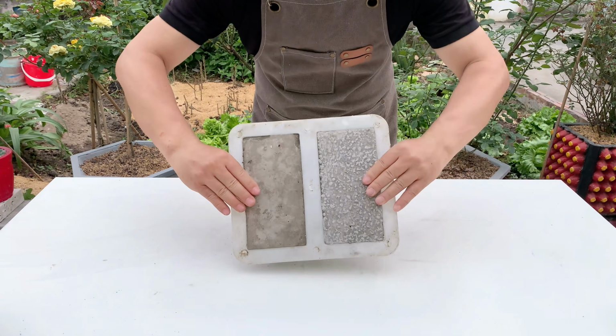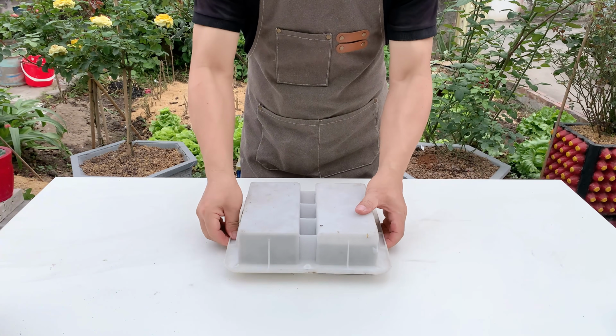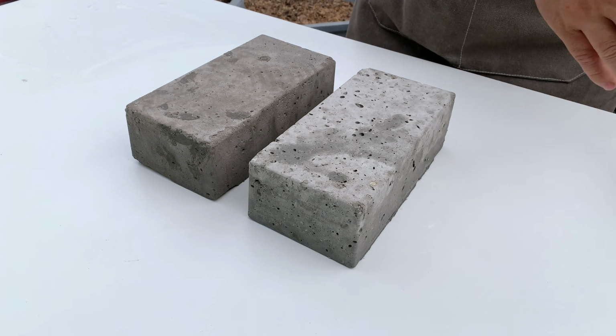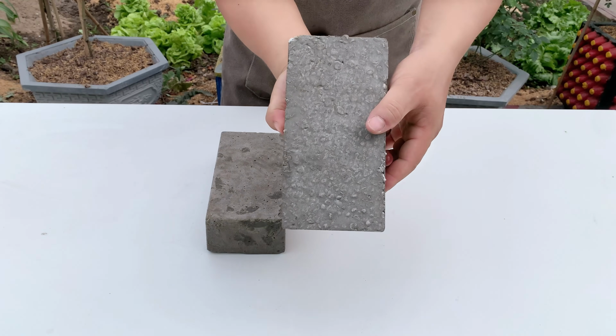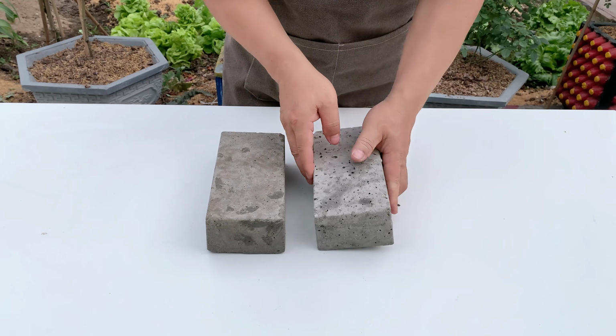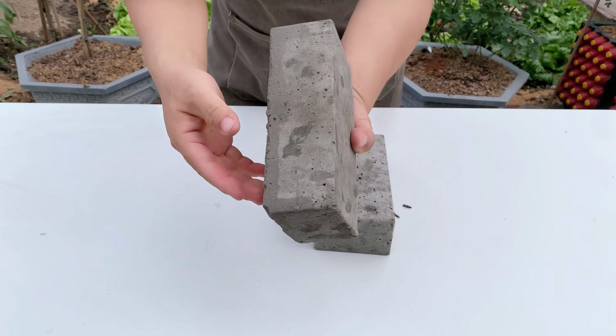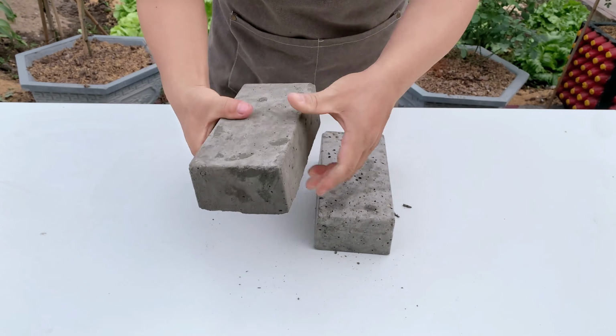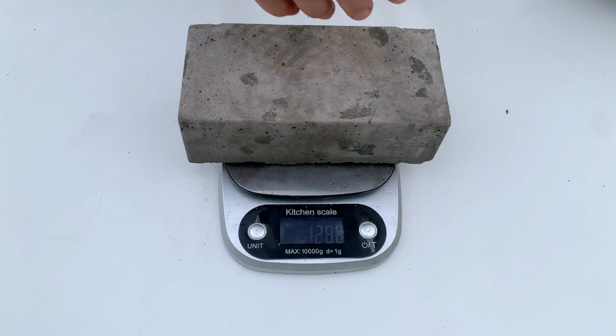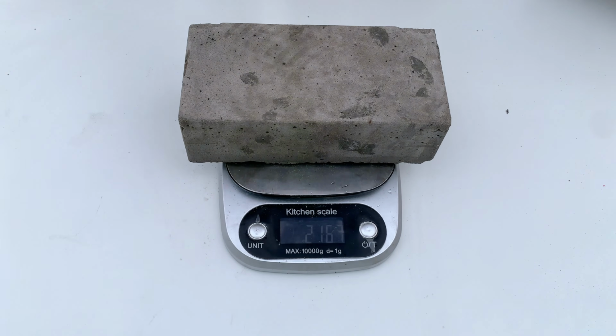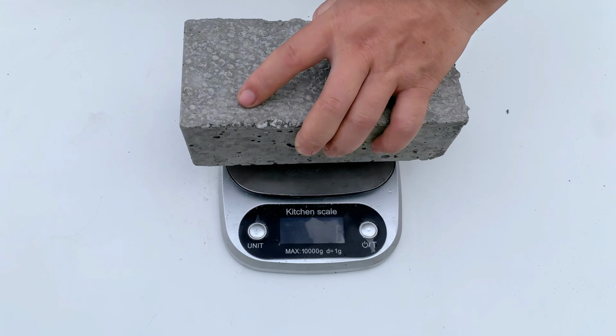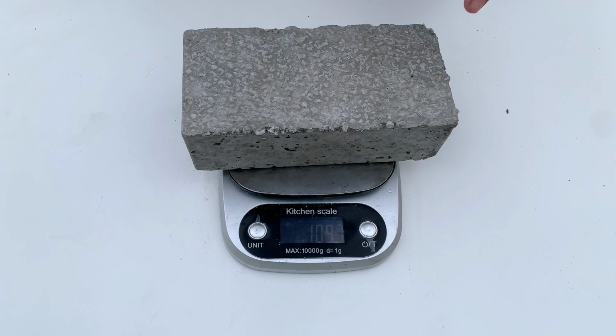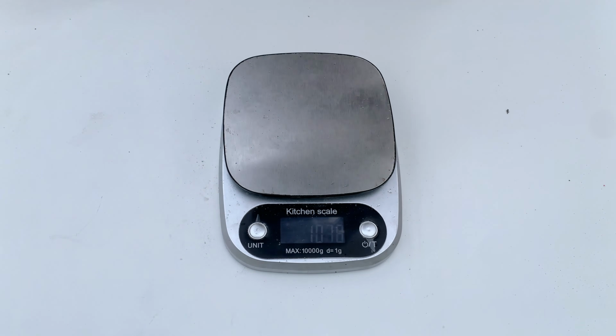Now both molds are left alone to cure completely. 7 days later, it's finally time to compare the results. First, the normal concrete block goes onto the scale. 2.1 kilograms. Pretty solid, pretty heavy. Now let's test the foam concrete version. Only 1 kilogram. That's a huge difference.